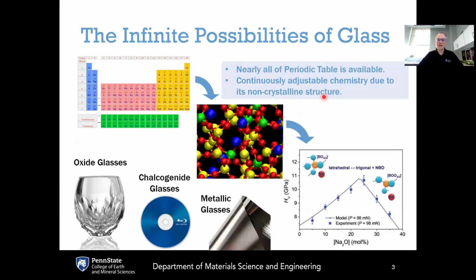And what this means is that from a chemical point of view, there are an infinite number of possible glasses available. Glass isn't like a crystal, where a crystal needs to satisfy certain requirements with respect to the stoichiometry of the crystal to define the unit cell that gets repeated infinitely in each direction. As a disordered non-crystalline material, glasses don't have to satisfy those same rules of stoichiometry because they don't have a unit cell.